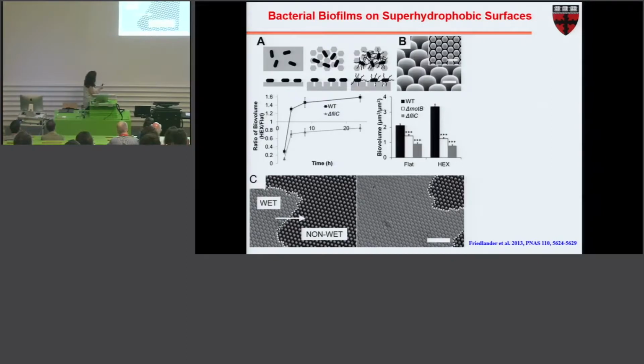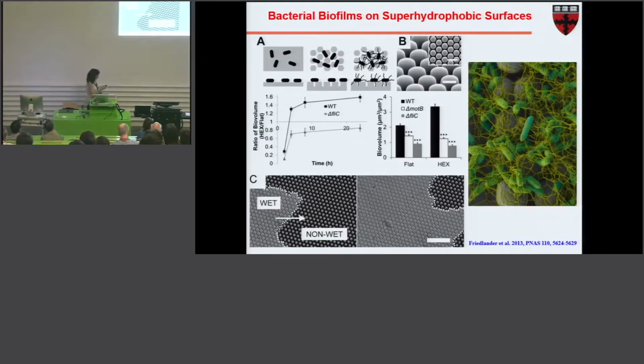So as the flagella experiences the interface, it physically forces, not even chemically in this case, into the crevices, and the moment wetting occurs, it undergoes a transition from superhydrophobic to a highly wetting state. Now bacteria can attach on any side you want, and the outcome is that you will have a very well developed bacterial community on the surface, even though it's superhydrophobic to begin with.